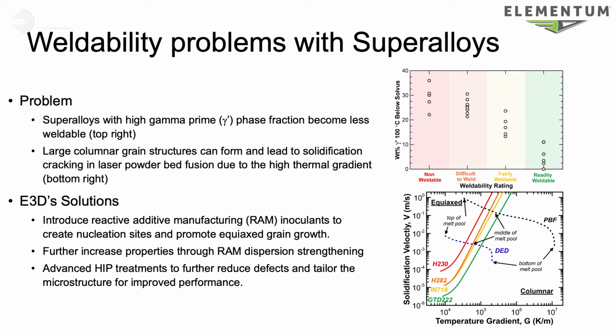Jeremy, can you speak to some of the challenges that these particular material systems present with the additive powder bed fusion approach? The printability, and it's well known actually, even the weldability of the nickel superalloy family varies. There are some that are considered quite weldable, others are either very difficult to weld or even considered non-weldable.